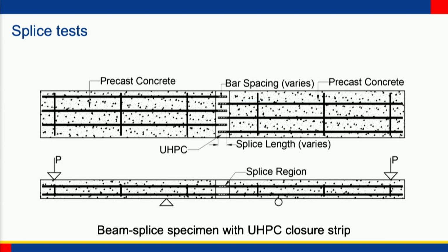Okay, we have 2 precast sections, and if you look carefully in the middle, there's a splice region. That's our closure strip, and we have bars at both the top and the bottom. The top bars simulate reinforcing steel. At the top layer of a bridge deck, they have a 2.5-inch cover. On the bottom layer of steel, 1-inch cover. We wanted to test both of them, so we cast multiple test specimens.